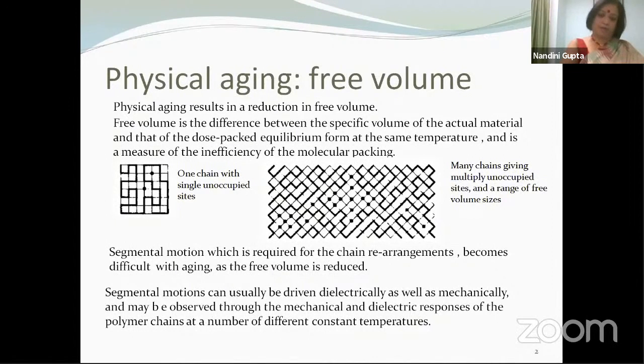So at a particular temperature, we expect a certain close packing of the molecules, which is the equilibrium situation. In practice, that is not achieved, and there would be certain vacancies left. For example, if you look at this figure on the left, here you have one chain, and you can see that every chain leaves one single unoccupied site. This could have been populated, and if it had been populated, the specific volume of the material would have been less. But that has not happened, and therefore we have a certain amount of free volume.